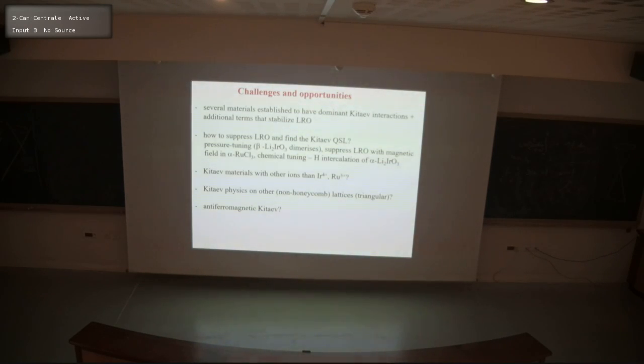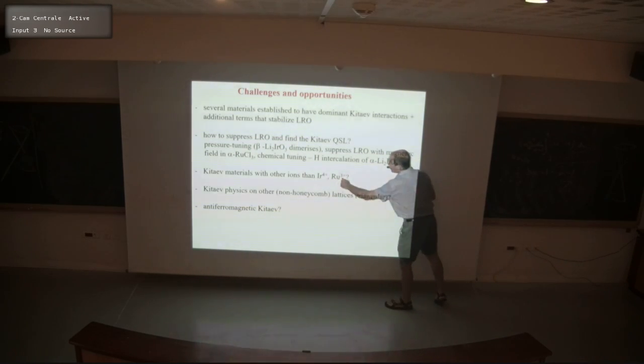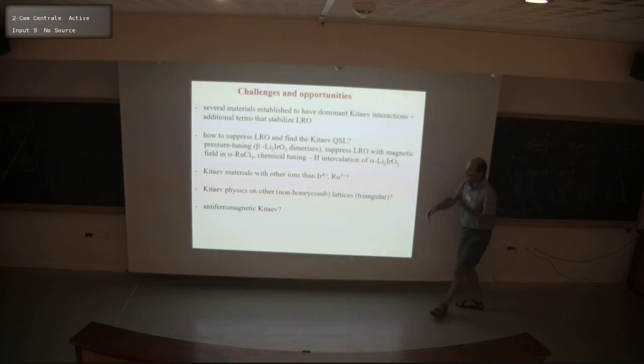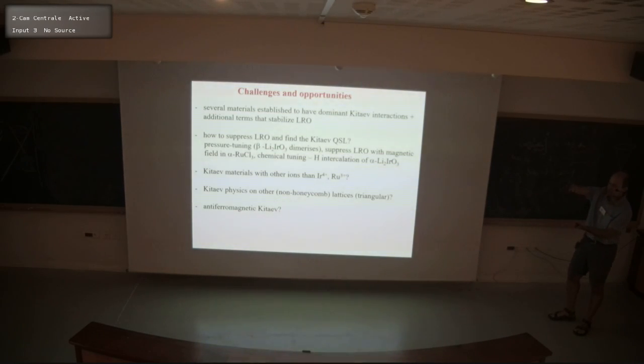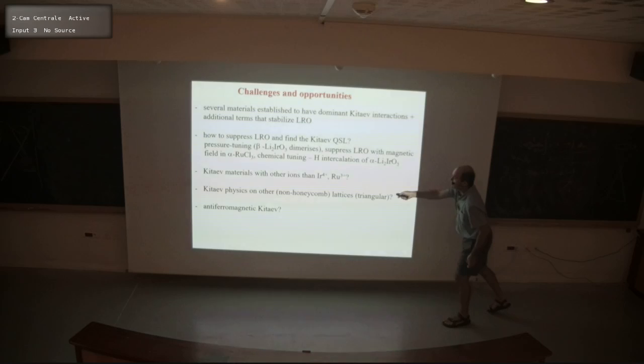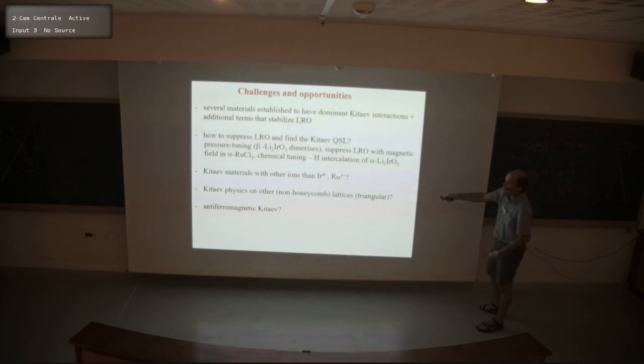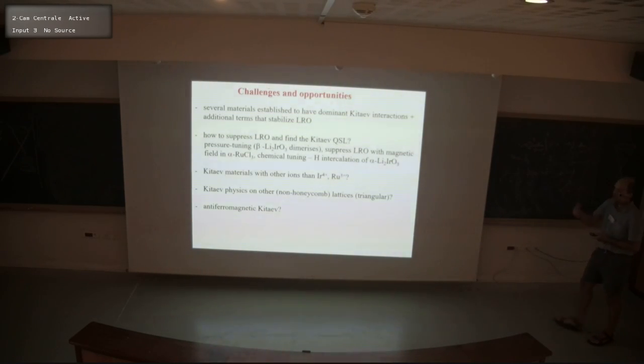Other issues that I'd like to point out is that so far all the Kitaev materials explored have been based on the magnetic ions iridium 4+ and ruthenium 3+. And in this case, even though the spin-orbit coupling is weaker, the local crystal environment is higher symmetry because we've lost the binding with the other layer. The layers are bonded by van der Waals, and so it allows the octahedra to expand to get closer to cubic. This is the reason why this still satisfies this J effective a half, even though spin-orbit coupling is reduced.